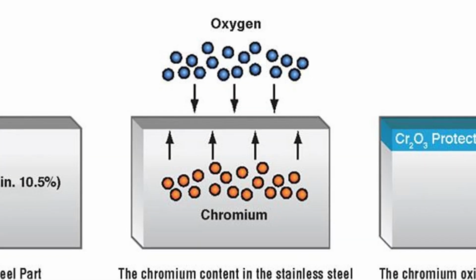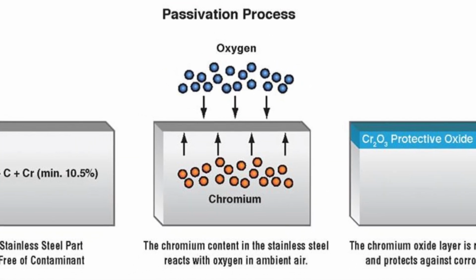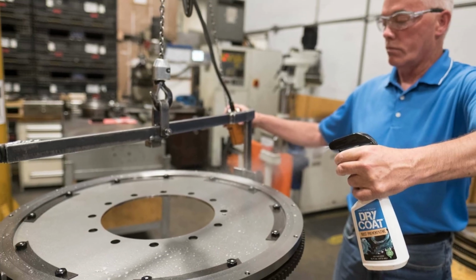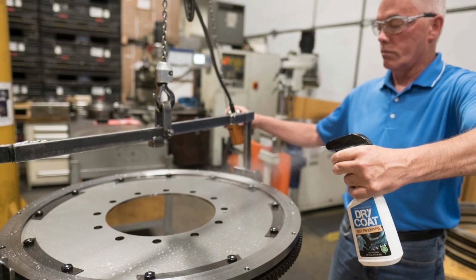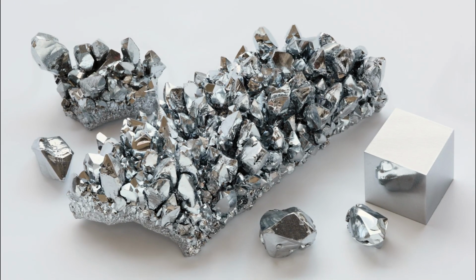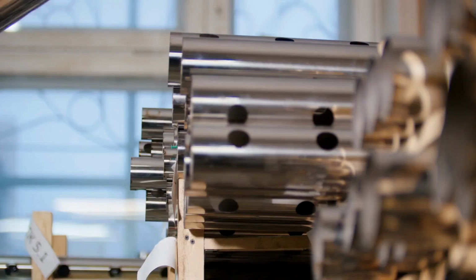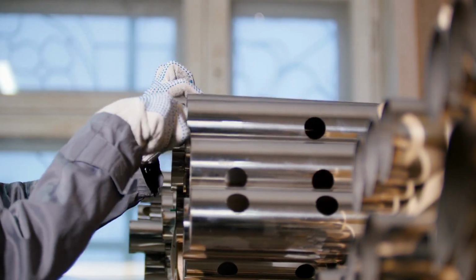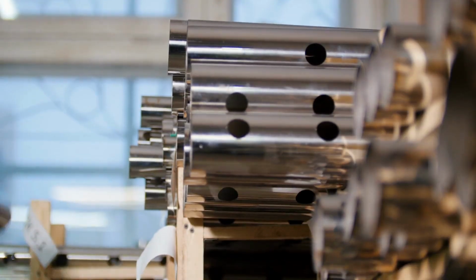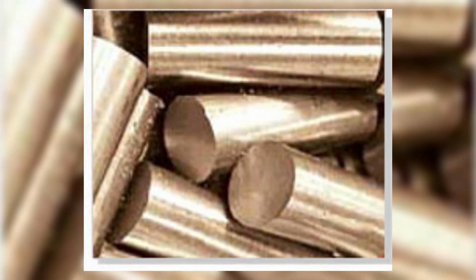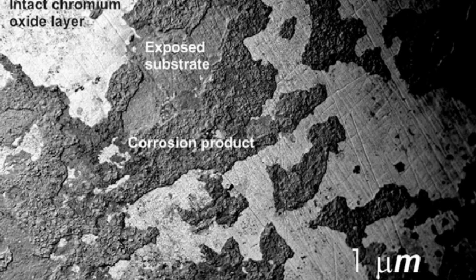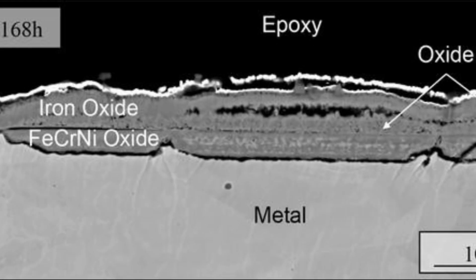The mechanism that Brearley had stumbled onto is called passivation, and it works through a logic that is almost the opposite of conventional rust prevention. Chromium, when present in steel at a concentration of roughly 10.5% or more by weight, reacts with oxygen in the surrounding air spontaneously and extremely rapidly. Before iron in the alloy has a significant opportunity to oxidize, the chromium has already done so, forming a microscopically thin, tightly adhering layer of chromium oxide across the entire exposed surface.